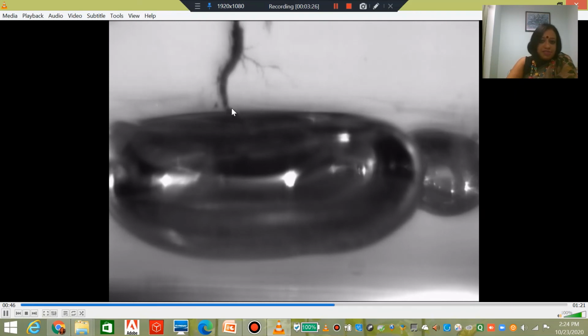So you can't probably see it very well anymore. Now it has moved to this region, and then this channel gets thicker and thicker, and then it moves here. So what essentially is happening is, if you remember, we started with a channel which was as filamentary as this subsidiary channel, and then because PD activity continued to happen within this channel, the channel became thicker and thicker, and now we really have a big eroded channel bridging the needle and the void. The needle can almost not be seen.